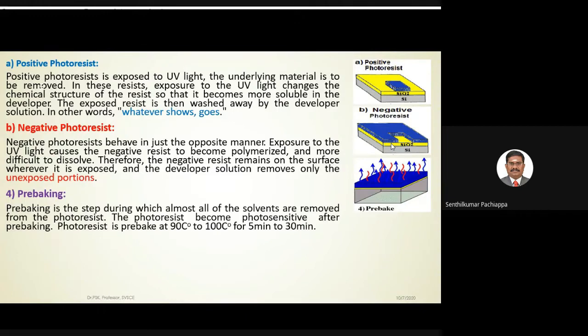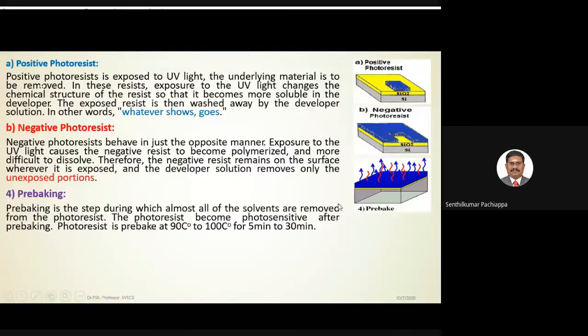Next one is the pre-baking. Pre-baking is the step during which almost all the solvent is removed. In this one we are using some solvent, and these solvents must be removed from the photoresist. The photoresist becomes photosensitive after pre-baking. Photoresist is pre-baked at 90 to 100 degrees for 5 minutes to 30 minutes.